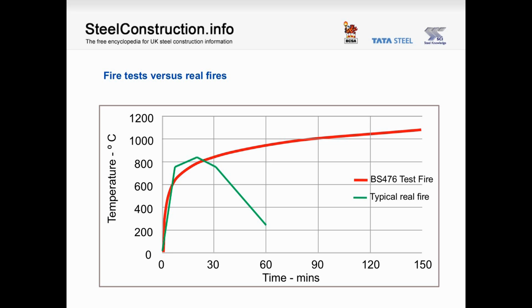This explains why the Basingstoke building, shown right at the start of this presentation, was able to survive a 4-hour fire with only 90 minutes fire resistance. It is because the fire was only at its most severe at a given point within the building for a limited period. This also tells us that many fire precautions in buildings may be overspecified, and if we can predict the temperatures within a fire compartment, we will be better able to match the fire precautions to the risk.